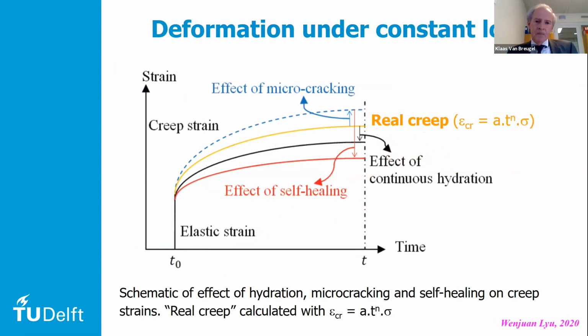When we look at a strain test, then the following could be the result of self-healing of a microcrack. Suppose you have here in the yellow curve the real creep, calculated with this well-known formula where we can calculate the creep in a not cracked sample. Suppose that you have during the test some hydration, then the creep will decrease because the stress-strength ratio is decreasing. Suppose that you have microcracking. Microcracking will cause an extra deformation. But if the cracks are healed and the material becomes stronger, then the effect of self-healing would be that you have a decrease of the creep strain compared to the creep calculated with the yellow curve.